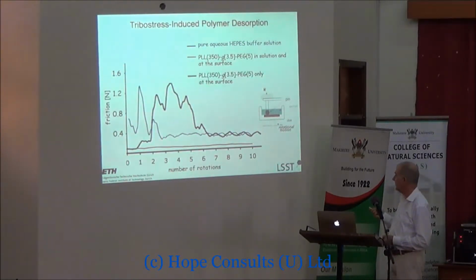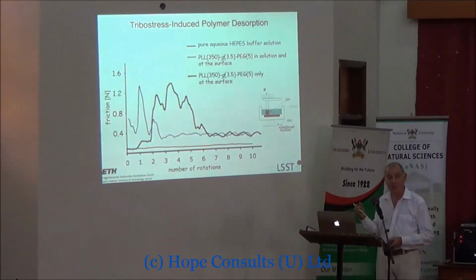And if we take pure water or a buffer solution, then we get a result that looks like this blue curve here. So quite a high value of friction, fairly noisy, and this should be friction coefficient. I'm sorry, this is wrongly labeled, but it's quite a high value of friction coefficient. If we put in the lubricant, the water plus the polymer I was just talking about, which we call PLL-PEG, we put the PLL-PEG in there, and we have a much lower value of friction, and it's very steady. If we put just a surface coating of the polymer in there, and we do the experiment underwater, then for the first rotation it lubricates, and then it looks like it's coming off, and we end up with the value of the pure water.